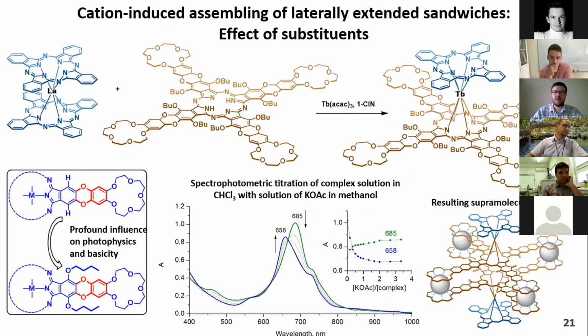At the next step, we decided to use another type of oxyanthracene cyanine containing additional butoxy groups in these positions of the macrocycle. These are the so-called non-peripheral positions, and we know that they provide molecules with very interesting photophysics and increased basicity. So introducing these substituents, we expected that we can gain more diversity in switchable properties of these compounds. At the first step, we decided to make a model double-decker complex containing one non-peripherally substituted phthalocyanine and one butoxy-substituted oxyanthracene cyanine. Its interaction with potassium acetate was characterized by the expected bathochromic shift of the Q band, which was typical for the formation of the dimer. So at this step, we understood that at least for formation of dimers, these butoxy groups are not an obstacle.